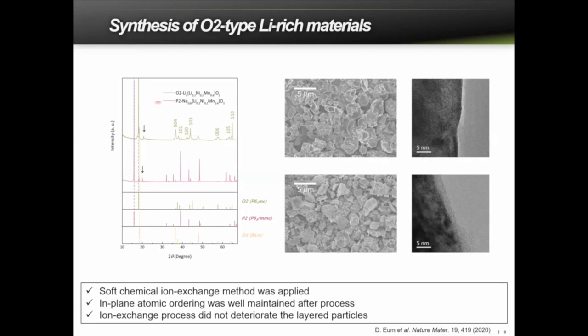So this shows the final products. As you can see here, the X-ray diffraction patterns on the left confirmed that we successfully obtained the O2 type layered lithium excess material from this P2 type sodium phase. And the particles were around a few micron in size, as we can see from the SEM pictures.